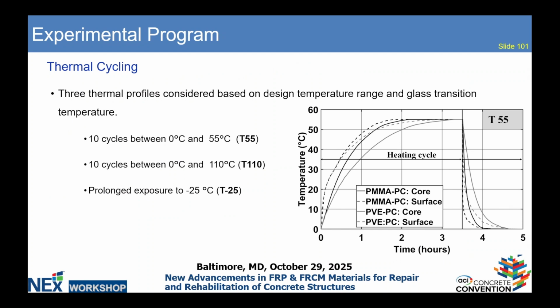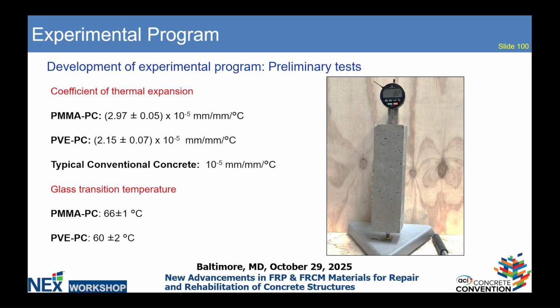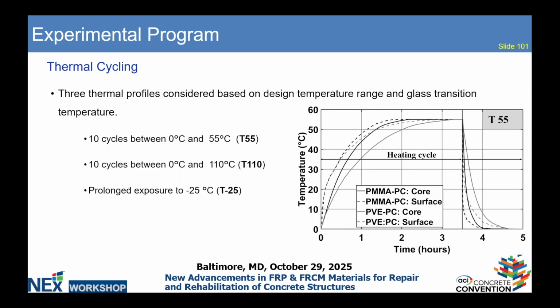Now on the thermal cycling part, as you saw, the glass transition temperature is somewhere around 60 degrees Celsius. So we wanted to do 2 thermal cycling. We did 10 cycles between 0 and 55 degrees Celsius, and 10 thermal cycles between 0 and 110 degrees Celsius, which are denoted as T55 and T110. On top of that, we also wanted to see the behavior of polymer concrete at extreme negative temperature, which is minus 25 degrees Celsius. So we had 3 thermal conditions.